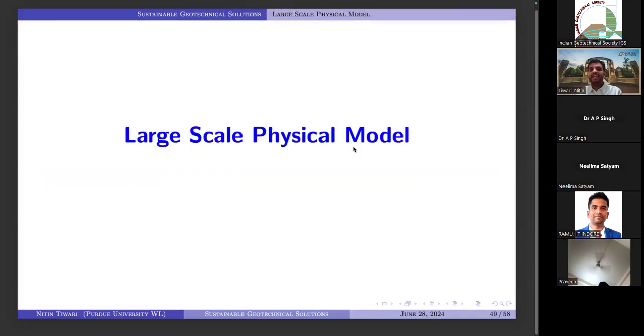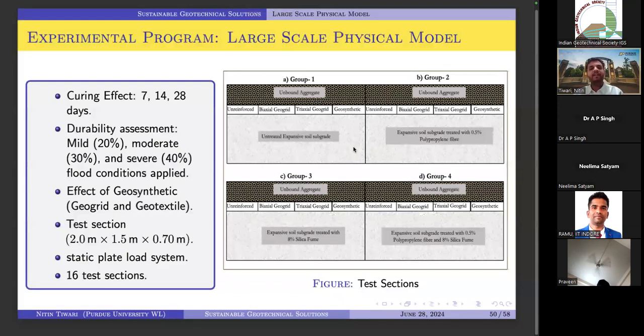Coming to the large scale physical model, I'll go very quickly. Whatever we found in the lab to be optimum, we used as an unbound pavement. We used the untreated subgrade with biaxial geogrid, triaxial geogrid, and geosynthetic geotextile, and the same with the subgrade treated with polypropylene fibers, silica fume, and the combination. Here we simulated 20%, 30%, and 40% flood conditions, and we used geogrid and geotextile. The test section was 2 meters by 1.5 meters by 0.7 meters. We used the static plate load test, and we conducted 16 test sections for this analysis.